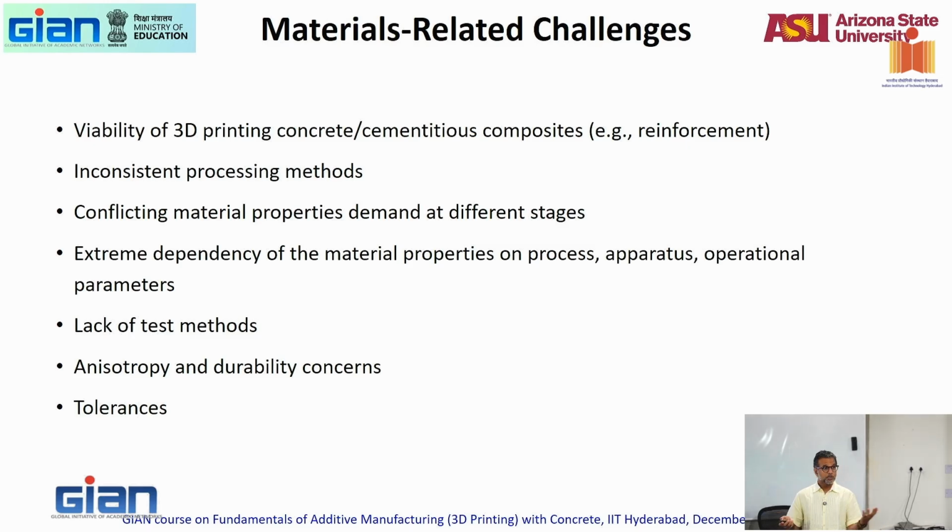Anisotropy, durability, tolerances. How much tolerance can you afford, or lack of tolerance can you afford? Now, you have to account for the fact that when you put a layer on top of a soft material, you might say, I don't want you to deform, but it is going to deform, right? There is short-term deformation, there's long-term creep. And that long-term is really not long-term. Even in rheology, there is creep. There's creep in one day.